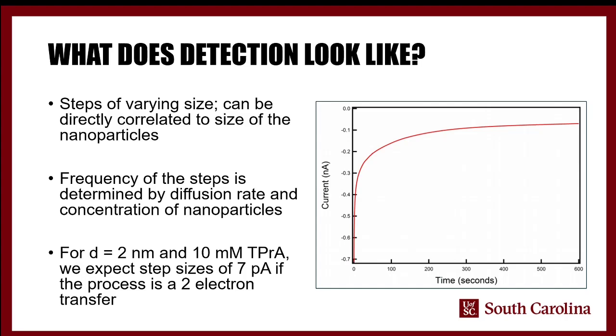So if something wonky happens, and the frequency ends up being a little bit higher, it's okay. Our measurement speed is typically on the order of milliseconds. So if we're aiming for less than 1 collision per second, that gives us a lot of wiggle room to detect the collisions that are happening very close together without them landing on top of each other, such that we can't differentiate.